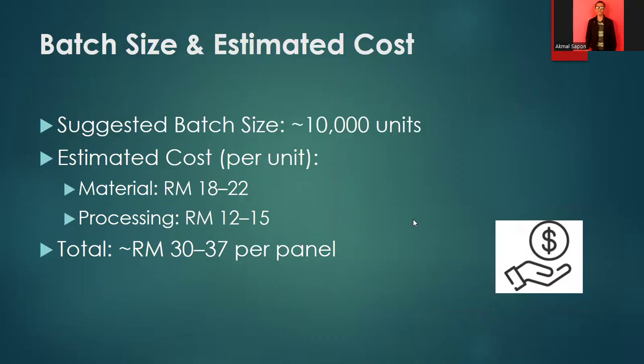So based on typical production economics, we recommend a batch size of approximately 10,000 units. At this scale, tooling investment for thermoforming becomes cost-effective. However, the size can be increased with automation. The estimated material cost per panel is between 18 to 22 ringgit, while processing costs are around 12 to 15 ringgit. This brings the total cost per panel to roughly 30 to 37 ringgit, which is competitive with current plastic-based door panels.